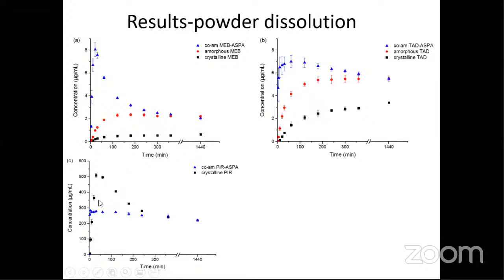But this case is a little bit different. We don't have too much time, so I won't explain in too much detail. This is because crystalline piroxicam and amorphous piroxicam formed monohydrates in the water. So the co-amorphous one dissolved very fast and formed monohydrates very fast, so the concentration stays like this. The crystalline one dissolved very fast and then formed monohydrates, decreased, and reached the same concentration. So this is a different case from the former two.